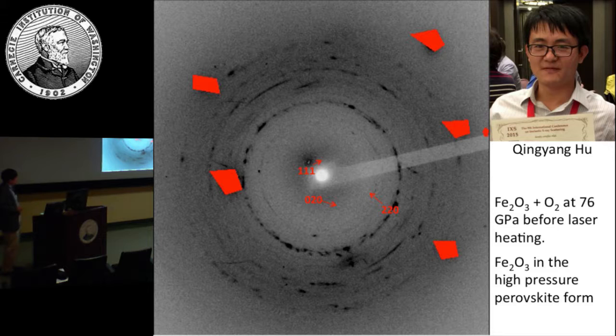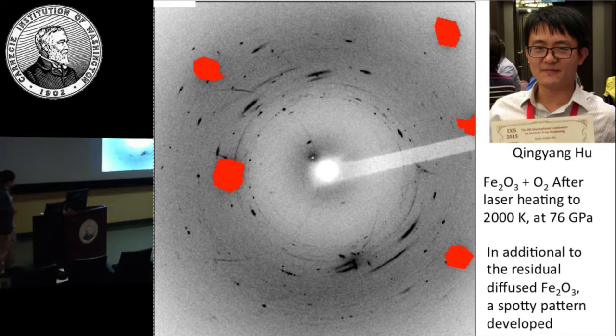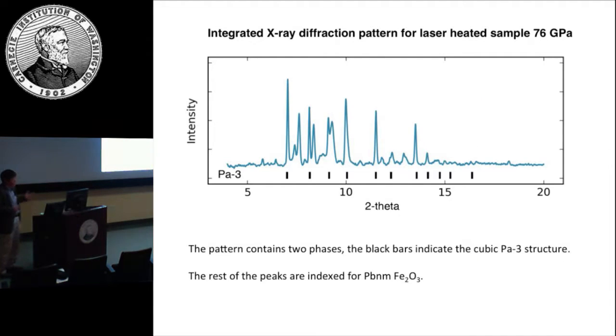Before laser heating, it's just the high pressure phase of hematite. This is known, and there is also the X-ray diffraction of oxygen. So this is the X-ray diffraction pattern. But once it was heated, it formed some spots, and this is not hematite, not oxygen. It's a spotty pattern that doesn't seem to fit anything known. And here we know FeO2 is a possibility.